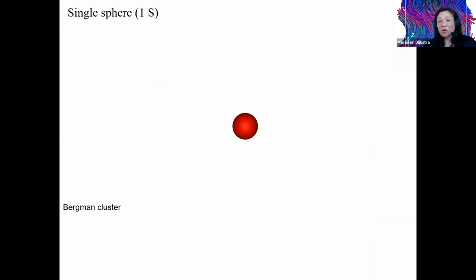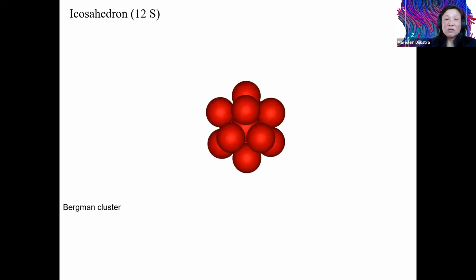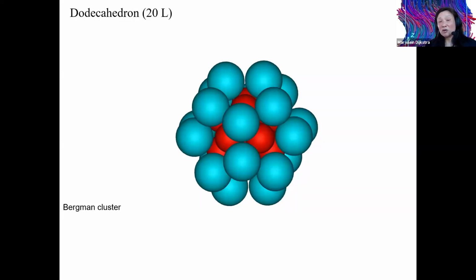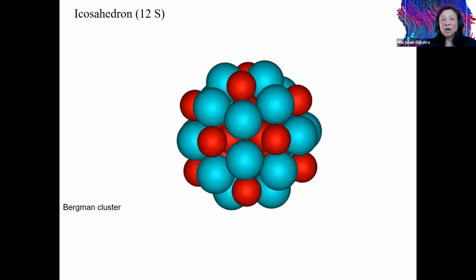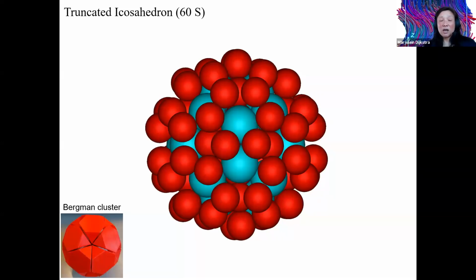So we can also peel off all these layers out of these clusters, starting with the center of this cluster. There's a single small sphere in the cluster. If we then add all these layers again around the single sphere in the center, we find an icosahedral shell of 12 small spheres around it. Then we find a dodecahedral shell of 20 big spheres around it. We then find an icosahedral shell of 12 small spheres around that center. This then is a truncated icosahedron of 60 small spheres. This is basically the Bergman cluster. So we have one subunit of the Laves phase now self-assembled into this icosahedral cluster.